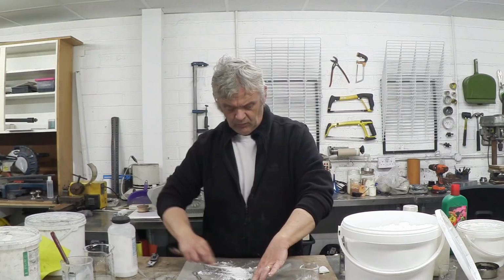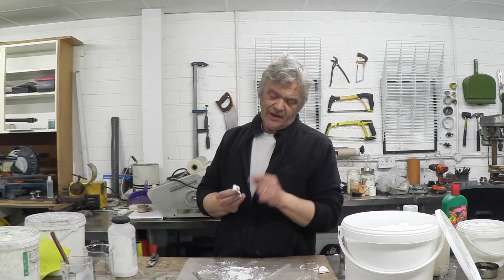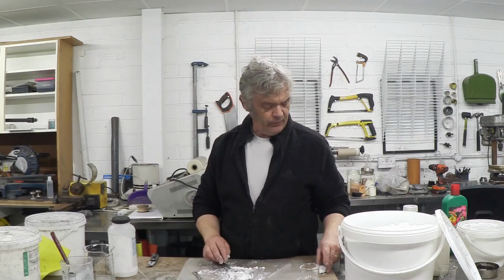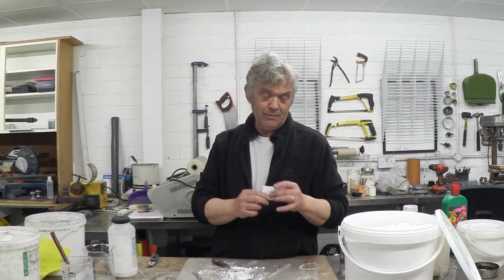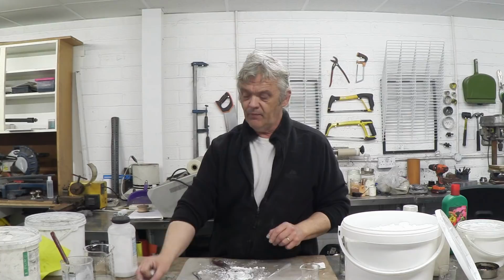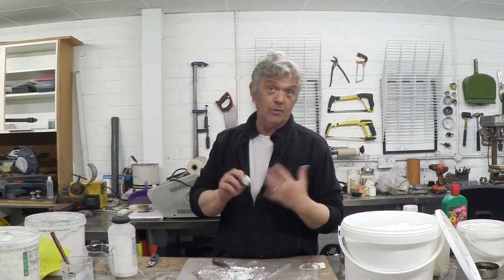And we make this beautiful white paste. That's got a much longer setting time. That'll take about an hour or two to set. And here's one that I made using that process. And that was made about an hour ago. It's still not quite set, but it is going much harder. It gets its full set strength over 7 days. So in this time, if we use only the powder and the chloride, we'll get a rock hard set very quickly, but with little strength, obviously. With this one, we get a longer set time.